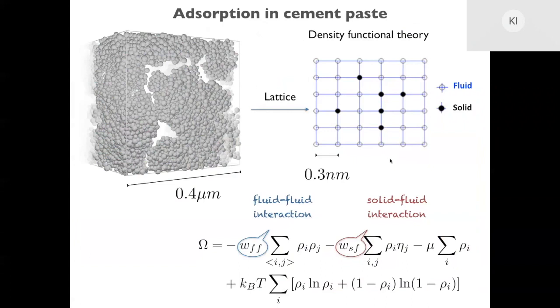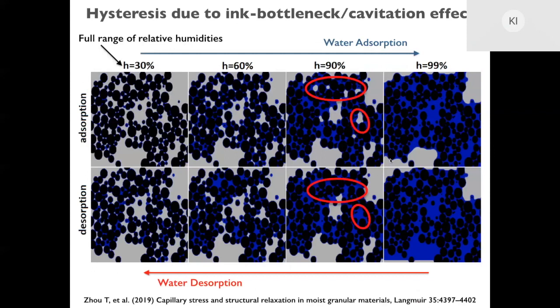And here a very important point is that we try to see how a piece of cement, which is around half a micron, is interacting with the fluid, the water, where water molecules are very small. They are 3 angstrom. So basically, we had to make a grid of this lattice that is as small as the water molecule in order to be able to use a mean field theory for this. So with this, we were able to find the distribution of water. Here you see on the top the adsorption and on the bottom the desorption as the relative humidity is increasing and later decreasing. And this is the example with water.